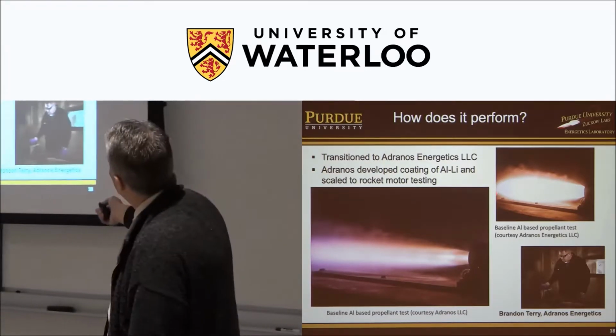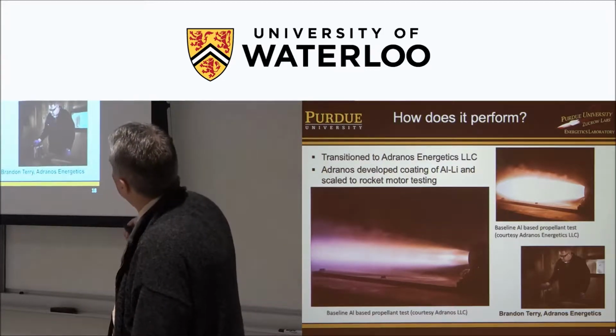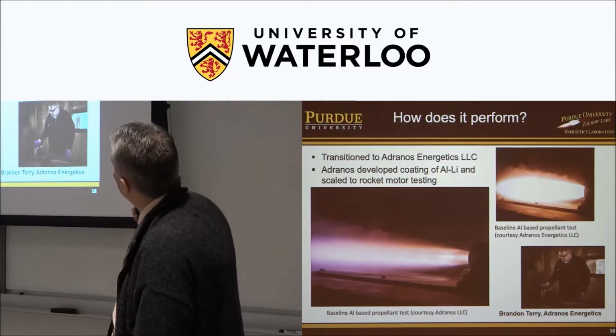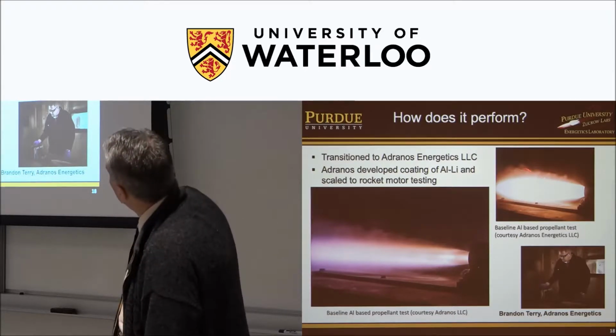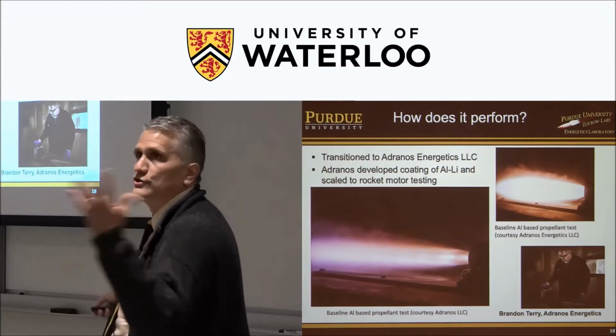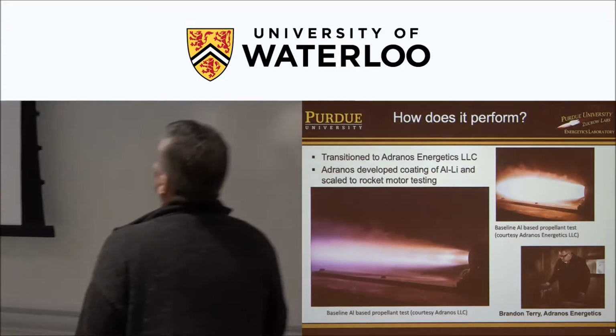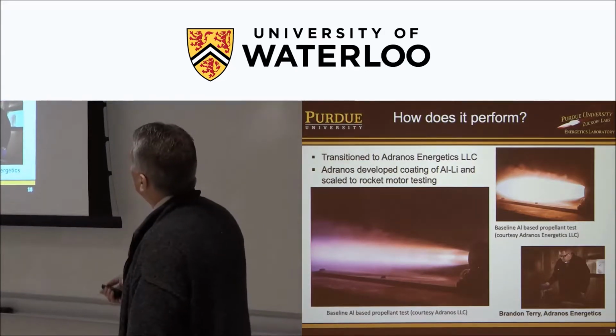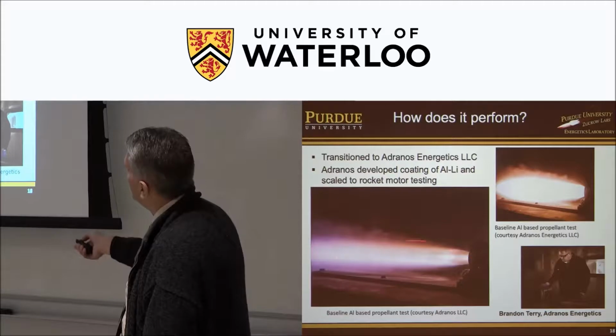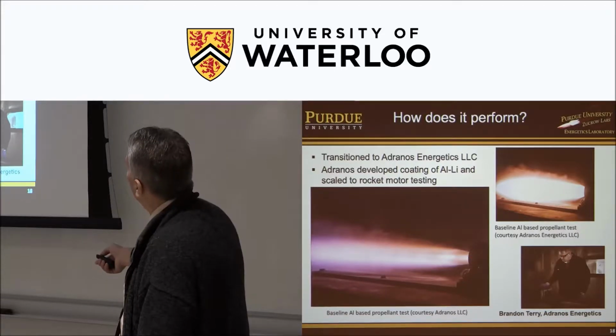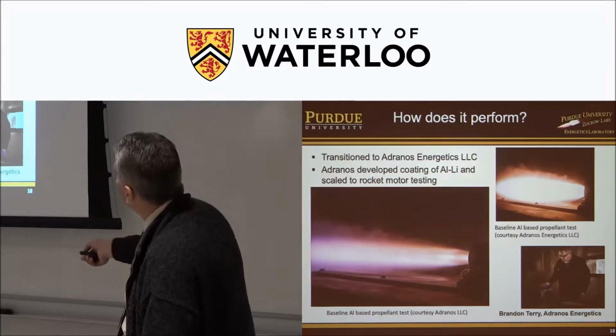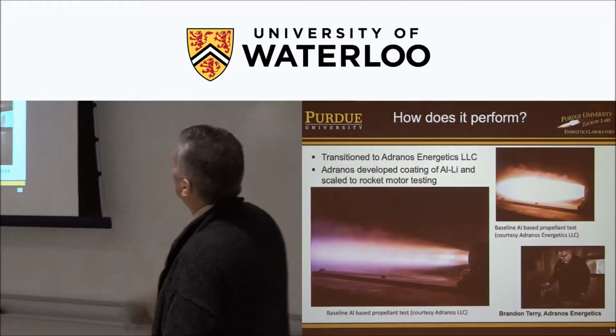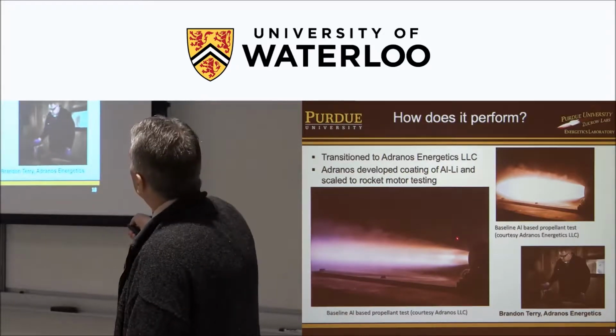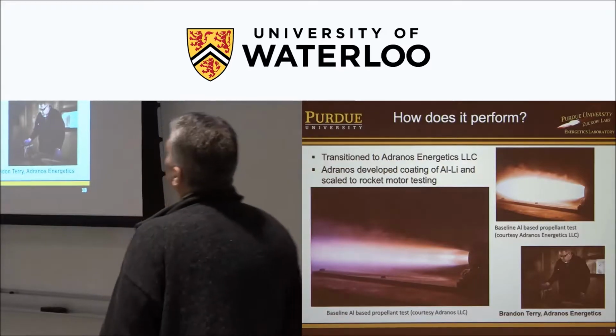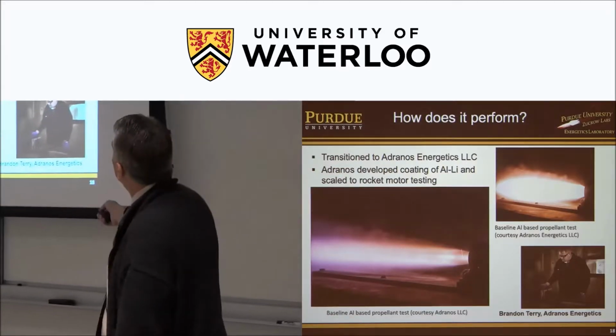And this is the baseline aluminized propellant. The same exposure on the camera. So this is a lot brighter. If you look closely, you can see streaks. Those are large droplets, maybe unburned aluminum particles coming out of the nozzle. In contrast, the aluminum lithium, I should have said aluminum lithium. I have a typo there. This is aluminum lithium. First of all, you see that you have the pink color and the plume is a lot less intense. It's a little lower temperature.